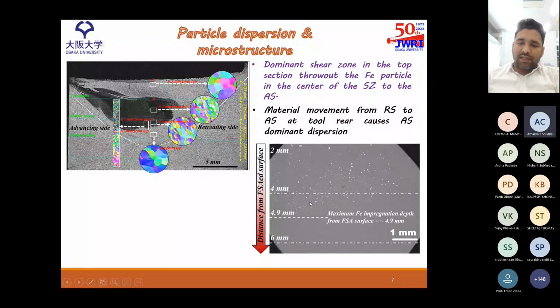So in the bottom region, as I said, there's a bimodal distribution. So we can see that in the upper bottom section, some particles can be seen, whereas in the lower bottom section, there is no particle. So it means that this is the iron deficient region and this is the iron rich region.